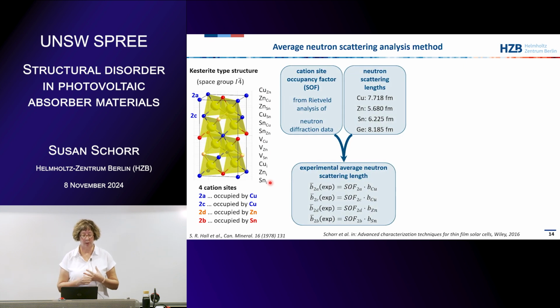So now we do the neutron diffraction experiment, and we analyze the data as usual, done with powder diffraction data by Rietveld refinement. And one parameter you get out of the refinement is the so-called cation site occupancy factor. And this tells you if the site is fully occupied or not fully occupied, and it also tells you the scattering power of the site.